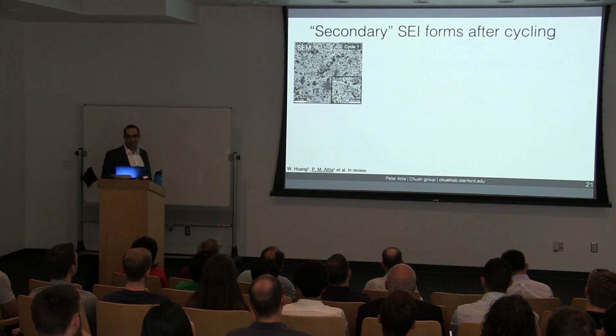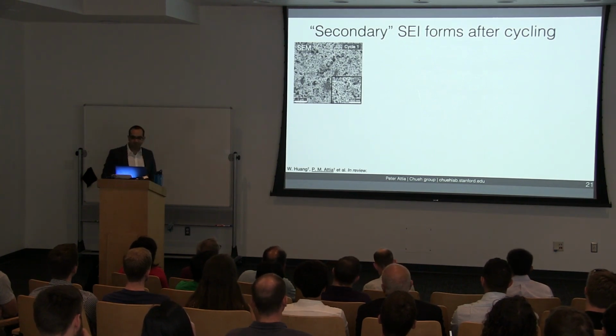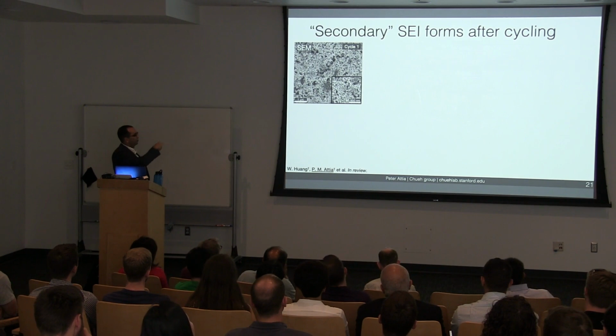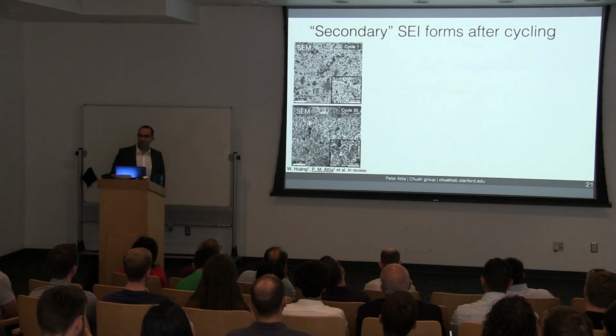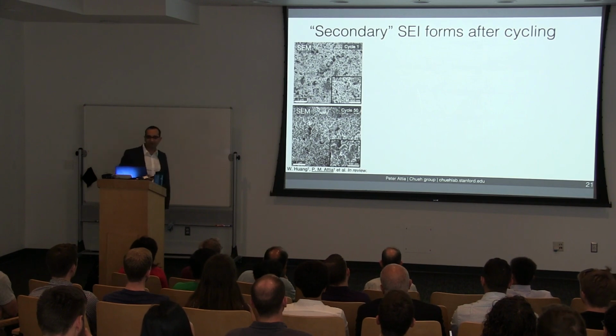We also noticed something interesting about the electrodes after many cycles. We actually don't even need Cryo-EM to first notice it. If you look at an SEM image of a carbon black electrode after one cycle, we basically see what we expect. We can clearly make out individual particles. After 50 cycles, we see this very goopy stuff covering the carbon black electrode.